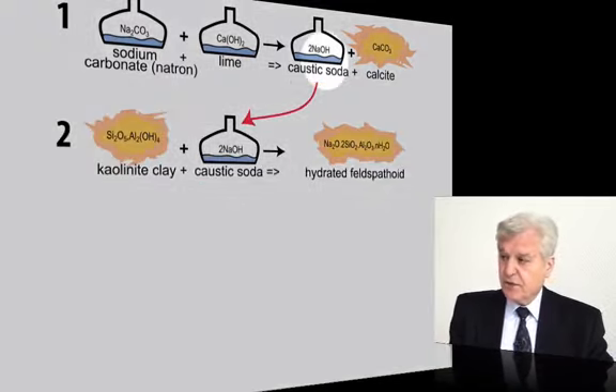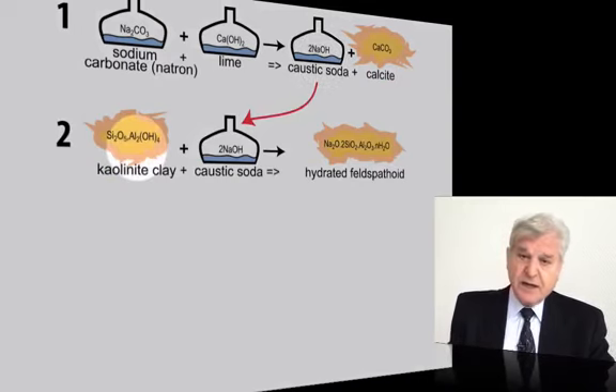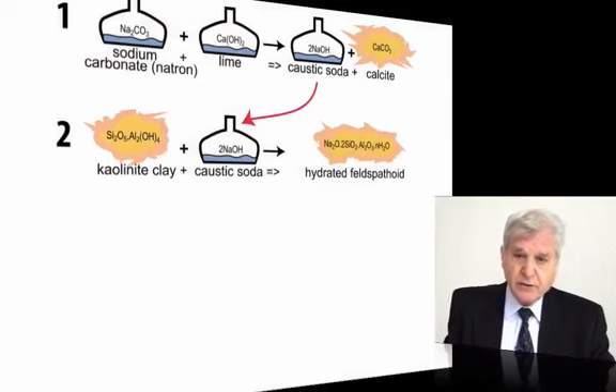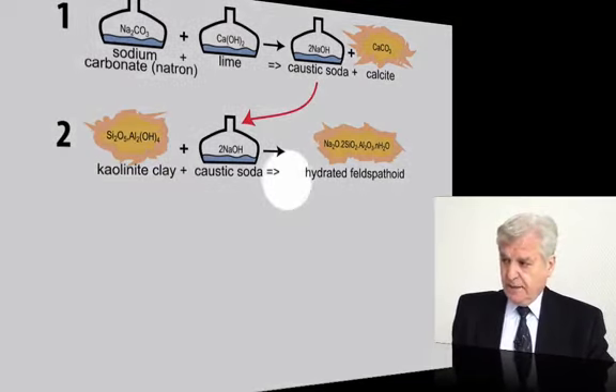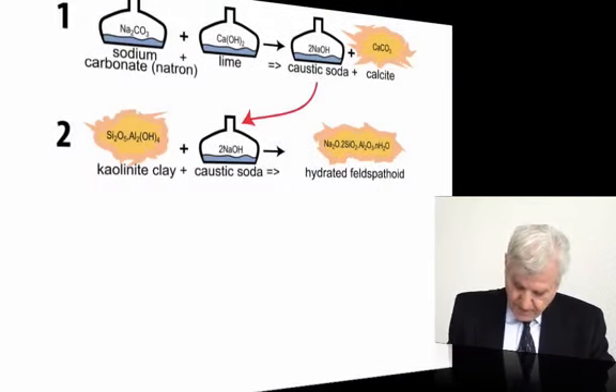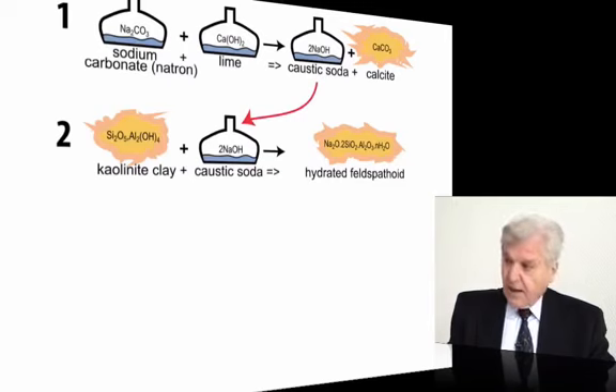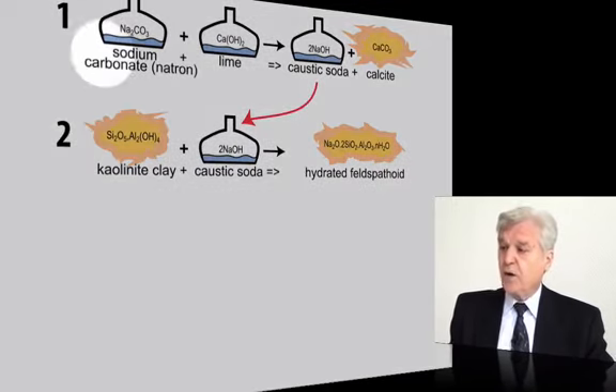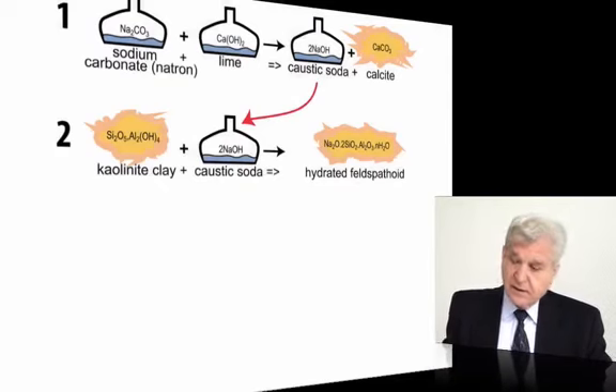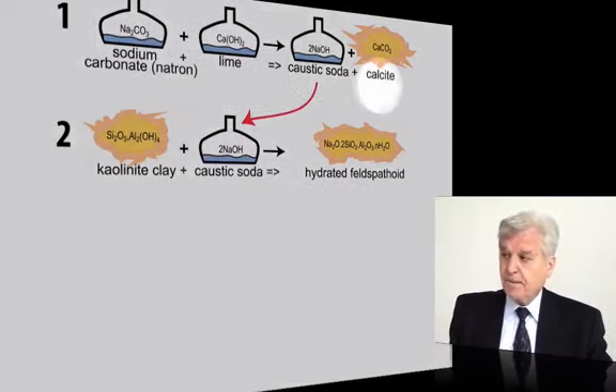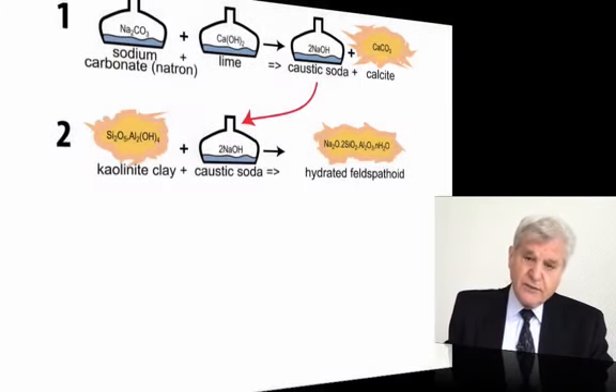Then caustic soda is reacting with kaolinitic clay. This is one of the basic reactions that we know in geopolymer chemistry, and we get what is called here hydrated feldspathoid. The pH is around 13 to 14, and if instead of sodium carbonate in reaction 1 we have sodium sulfate, then we will get caustic soda and the production of calcium sulfate, which would be then taken by geologists or mineralogists for remains of gypsum, which is not.